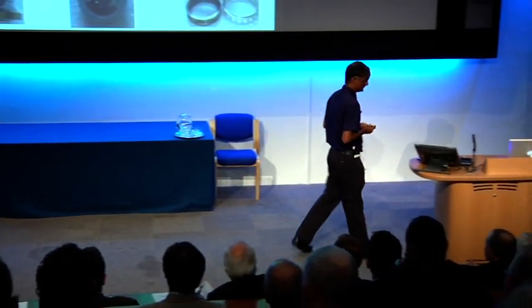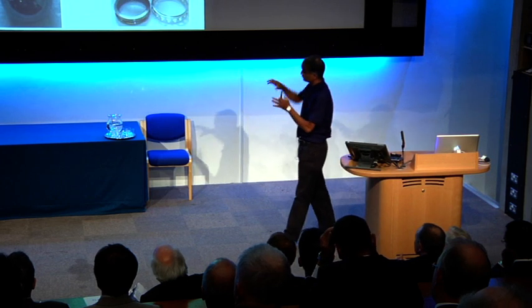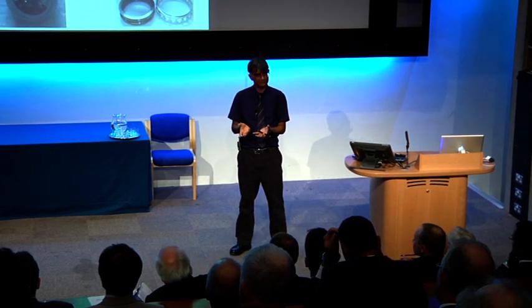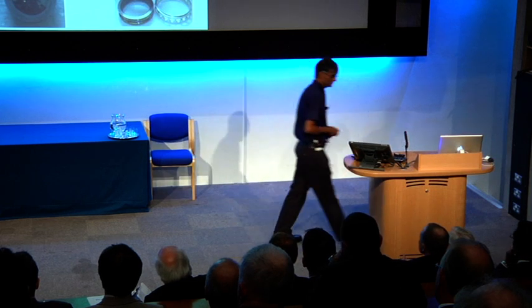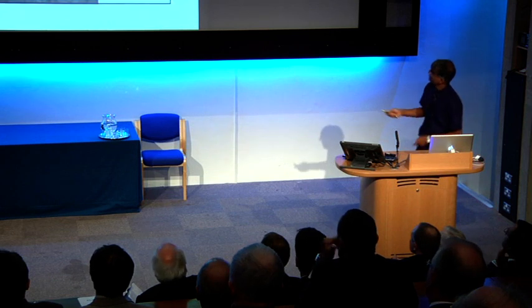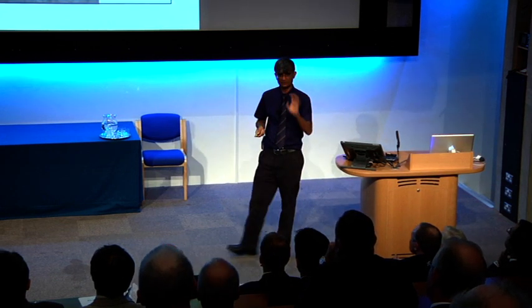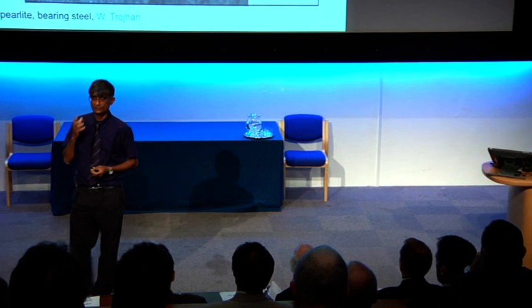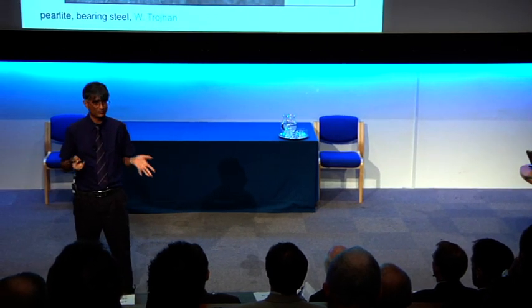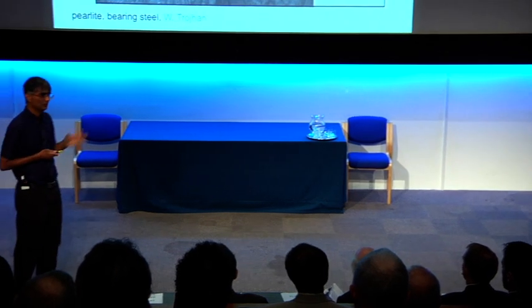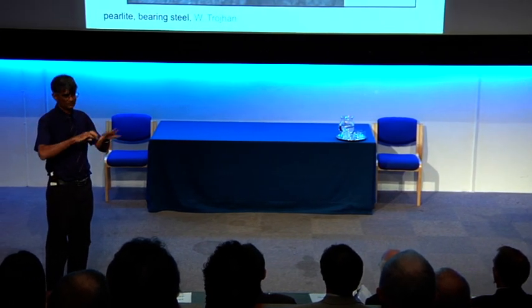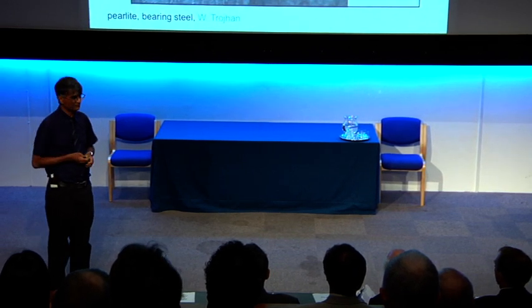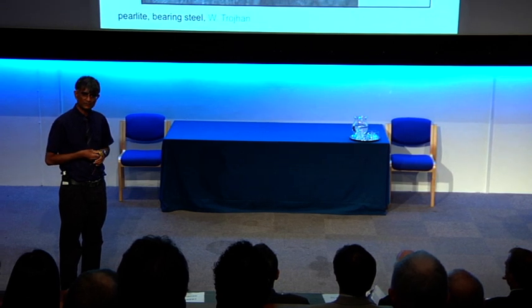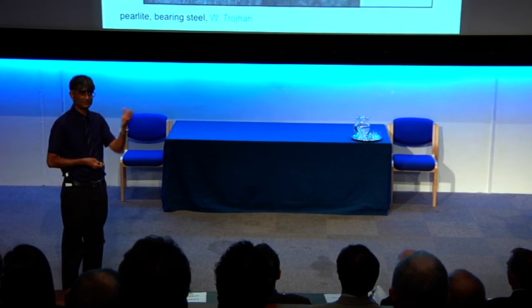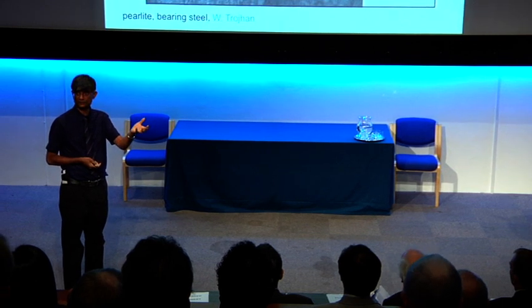Let's look at just one of these aspects to begin with, and that is that when you form these rings and so on, the material has to be soft, relatively soft. Okay? The structure, typically, of this steel is pearlite. Pearlite is written in the textbooks as alternating layers of cementite and ferrite, and this makes the material too hard to form into shape during the manufacture of bearing components. So one way is to heat treat it so that the amount of surface per unit volume between the cementite and ferrite is minimized, but that's a very expensive thing to do, just to hold it until everything's spheroidized. It's basically the same principle that if you take a soap froth and allow the bubbles to burst.